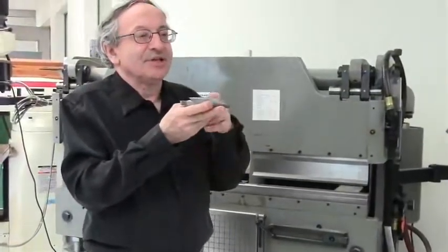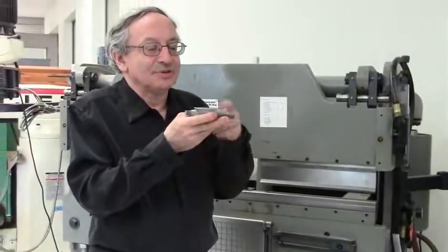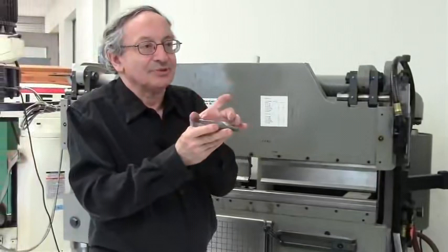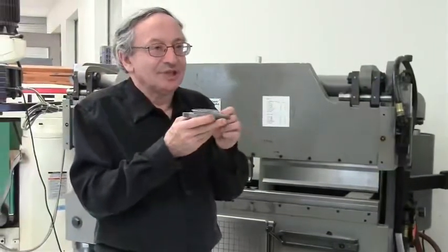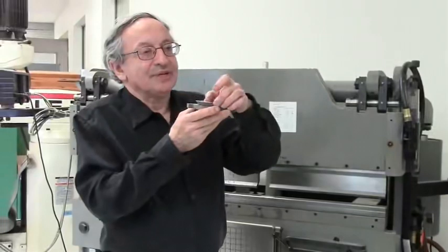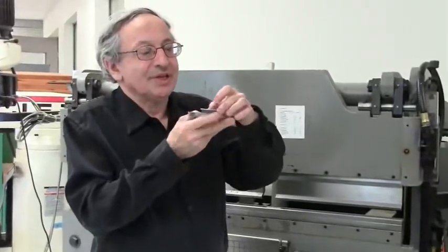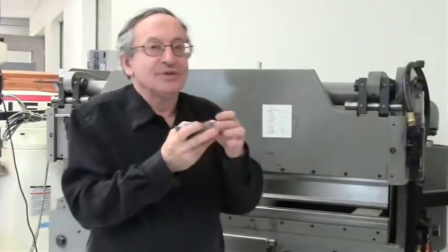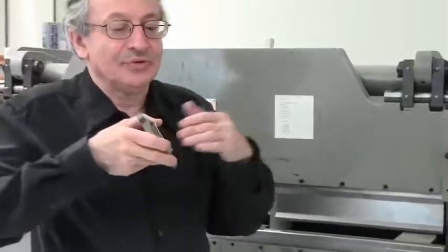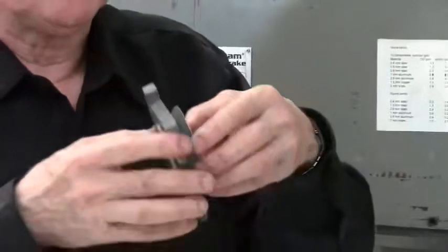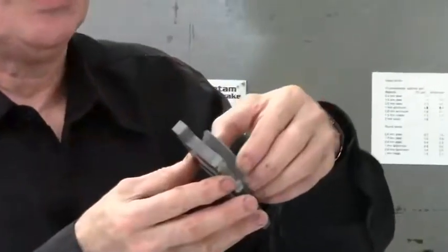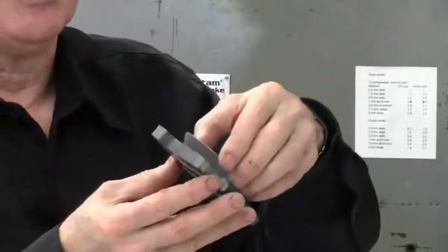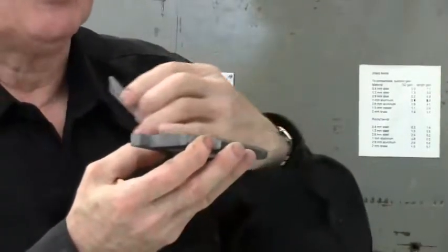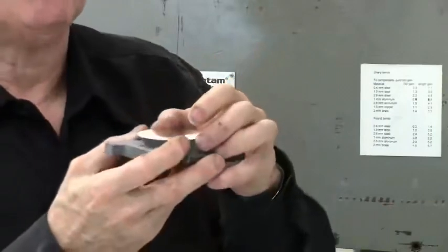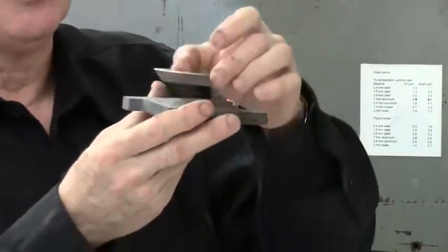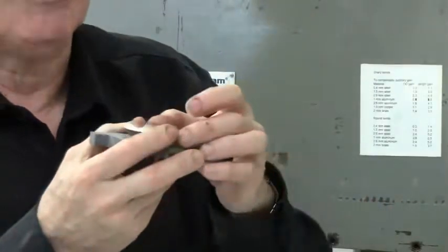First, the glass and the metal have different expansion coefficients, so you have to make sure over the size of the mirror it wouldn't be a problem. But you have to think of something else too. That bonding layer will expand with temperature 10 times faster than the metal. So if this mirror is just acting as a head-on mirror or 45-degree mirror, the problem is not very big, because if this mirror shifts parallel, usually it's not a problem. Let's say you have a 50 micron bond layer. Even if it changes 10% in thickness, it's only 5 microns. A 5 micron parallel shift is usually not a problem for a lens or a mirror.